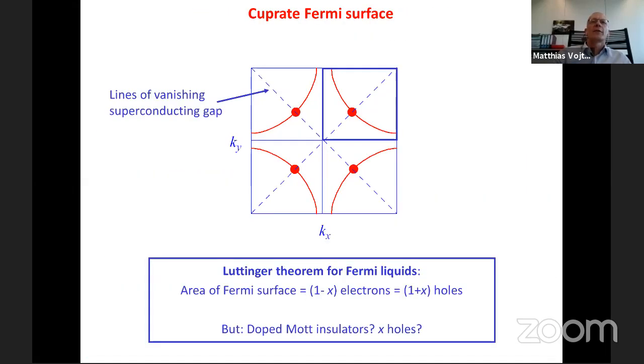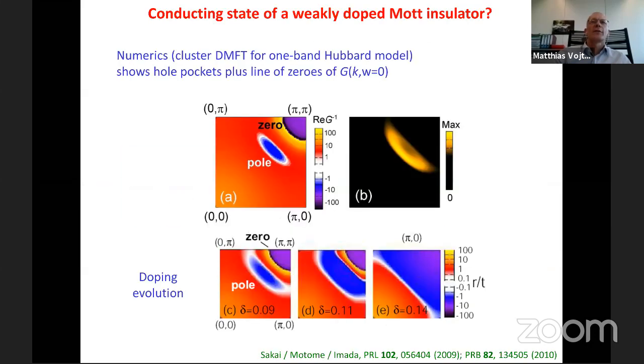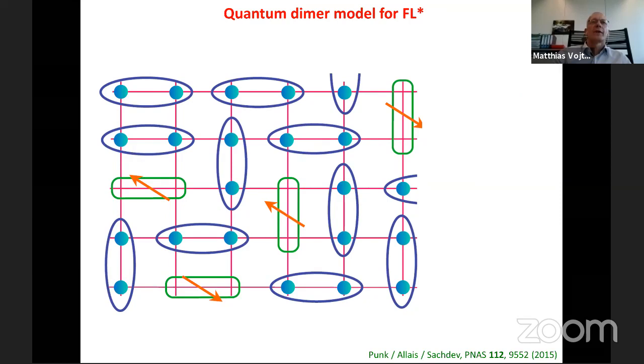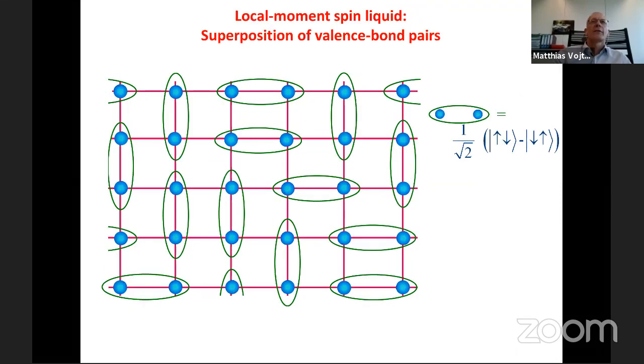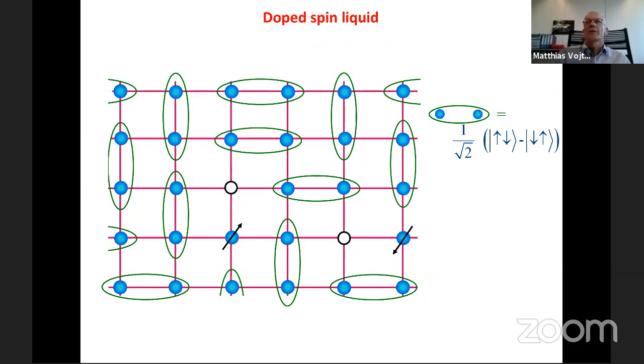So you're perfectly right. Cuprates in the simplest model are described by one band. And then there is no natural separation between the local moments and the carriers. One way to think about this, let me just jump to the right slide here, is to start from this one. Suppose we have this spin liquid to start with. So that's now an undoped spin liquid. And then we put in holes. That is the situation which would correspond to weakly doped cuprates. Then you see that in principle, if you dope holes, you also get liberated spins, right? Because you destroy a dimer.